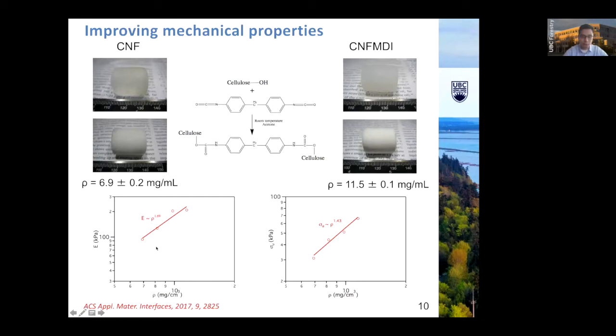And then we look at the mechanical properties. I show here the mechanical property increases non-linearly with the density, meaning the modulus, let's say Young's modulus, as well as the tensile and compression stress. It all increases with a power law equation, meaning we can make a lightweight material that is also super strong. This is by some simple modification after forming the hydrogel.